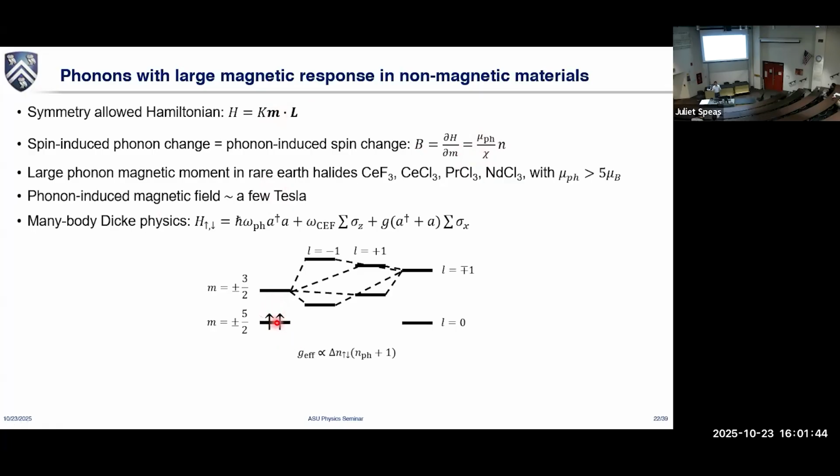So we flip the electron's spin, and then one of the couplings, because of angular momentum conservation, will become bigger, because you have more populations proportional to the number of electrons. And the other electron level is depleted, so its coupling is less. In which case you can see that the phononic state that carries different angular momentum will actually have different energy, and that difference in energy is proportional to how many spins you injected. That's essentially the effective Zeeman effect.